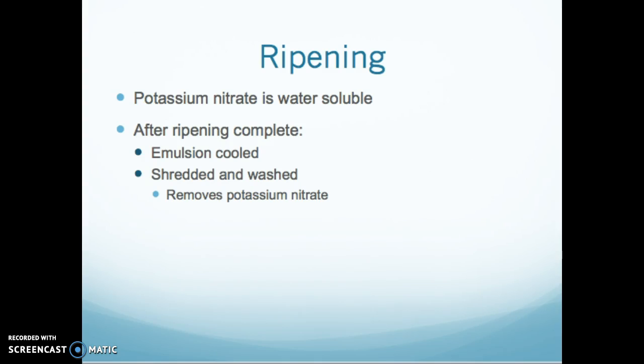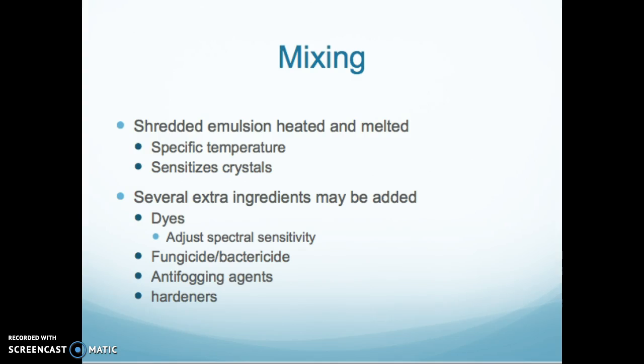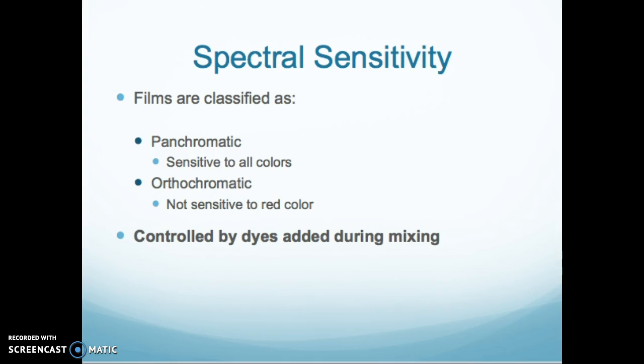Also, in your ripening, the potassium nitrate is water soluble. So after the ripening is complete, the emulsion is cooled, shredded, and washed, and that removes the potassium nitrate. Mixing: the shredded emulsion is heated and melted to specific temperatures and sensitized, and several extra ingredients may be added, such as dyes, the blue dye, a fungicide or bactericide, antifogging agents, hardeners, whatever is needed.